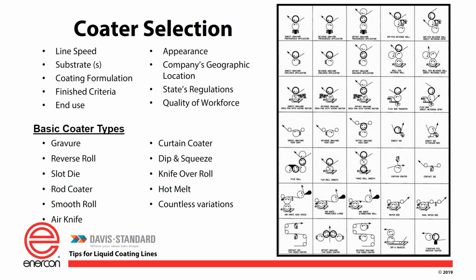Slot die, you know, if I'm doing the adhesive coating and we're going to run the same adhesive all day, a slot die is a great coater to put on there. However, reverse roll and a gravure and a rod would also work with those adhesives. Rod coaters are very low-cost coaters, which you put on an excessive amount of coating, like you put on more PSA than what you want, your adhesive, and you meter it off with a wire wound rod or an engraved rod in today's standards. Smooth roll coating, that could be considered for primer coatings, for your silicones. You don't really use it in the adhesive market, but for other coatings out there.